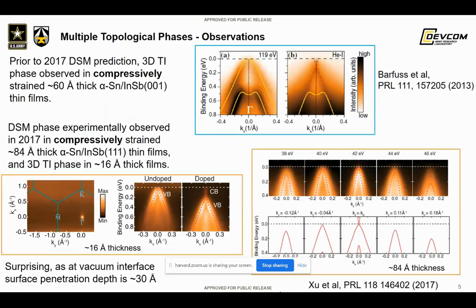Now, over recent years, it has become puzzling because people were able to achieve a variety of topological material phases, going from 3D TI to Dirac semi-metal as the thickness of grown layers of alpha tin is varied. And so this was somewhat confounding. I won't go into all the details, but from the slide you can see that a variety of phases were observed depending upon the orientation as well as the thickness of the materials. And this was quite puzzling.